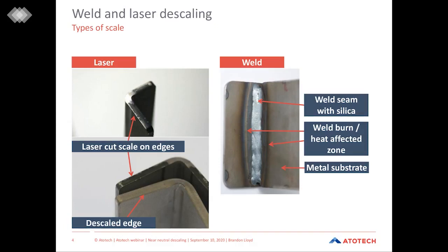If we move to the right side of the page, this exhibits a traditional seam weld. In the middle, this is the weld seam with the silica inclusions. Moving to the outside areas, like we referenced in the previous slide, you can see the weld burn or heat affected zone. And then lastly is the metal substrate itself.